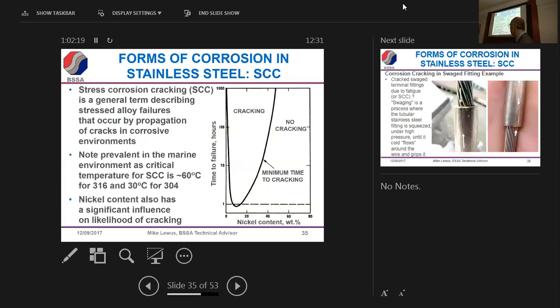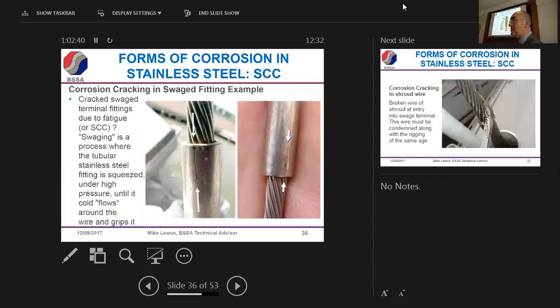I'm going to ask you a question from an example because it raises an interesting question. But you can see the effect of nickel. Duplex has high nickel, so you end up being more resistant to stress corrosion cracking. Superaustenitic are up here too. If you're around about 304, 316, you're actually least protected against stress corrosion cracking, which may or may not be an issue depending on ambient temperatures. These are the kind of things you do see: swage fittings and corrosion build up and then cracking.